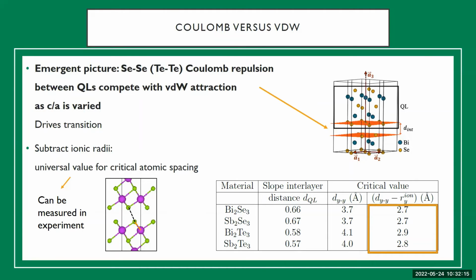And one interesting thing that we found was that at the critical point at the transition in each of these 4 materials, there was a universal value for the distance between atoms. So this is shown in the table, in the rightmost column. So we found that there was a critical distance of about 2.8 angstroms for the atomic spacing between quintuple layers. And this is interesting because this can be measured in experiment. So it can have an experimental signature as well.